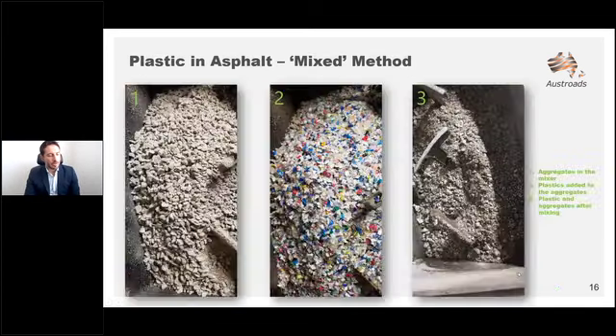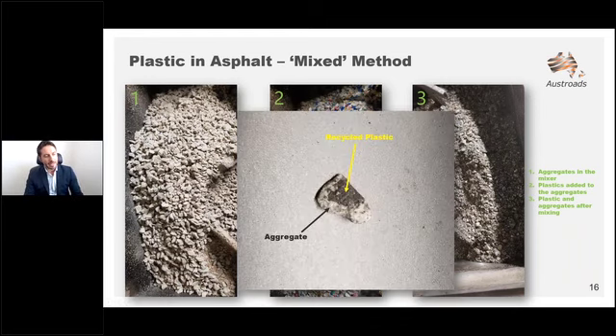If you want to see a few pictures about this process, at number 1 on the left-hand side, these are the aggregates in the mixer. Number 2, we just added, in this case, the commingled version of polyethylene and polypropylene you've seen before, onto the hot aggregate. And number 3 is the final product of the plastics melted around the aggregates before the bitumen is added. If you zoom in on number 3 and isolate one particle, this is how it will look, where you have an aggregate that may or may not be coated with recycled plastics. So this is the mix method procedure.